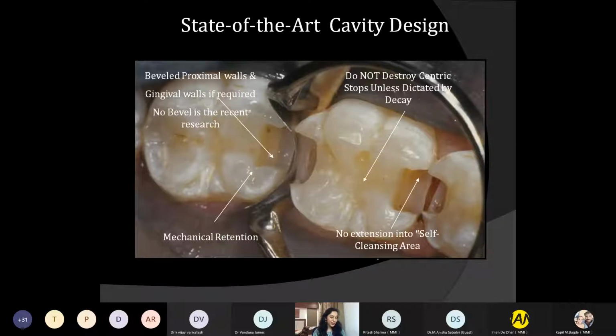So, like here, in this case, this is an occlusal facet, and this occlusal facet is surrounded by enamel. So, even if you give less amount of composite, this will really work very well over here. But what about an occlusal facet, which is in dentine? If you give only 0.2, 0.5 millimeters, you don't prepare that facet, and you don't give a bulk of 1.5 millimeters in dentine, your restoration will chip off. Now you understand why restorations chip off if they are only in dentine, surrounded by dentine all over and no enamel.